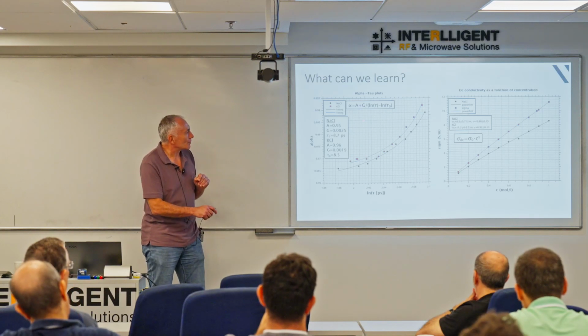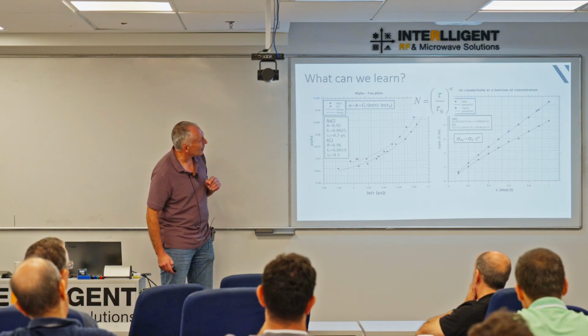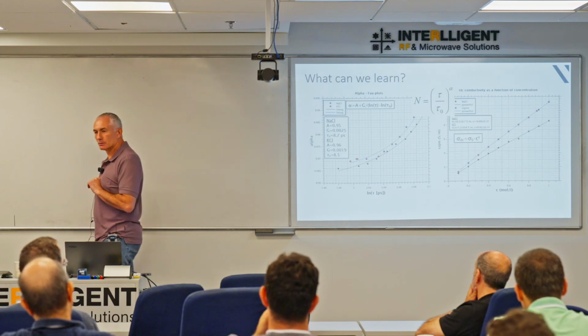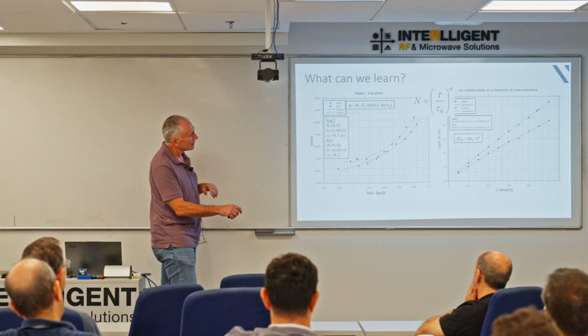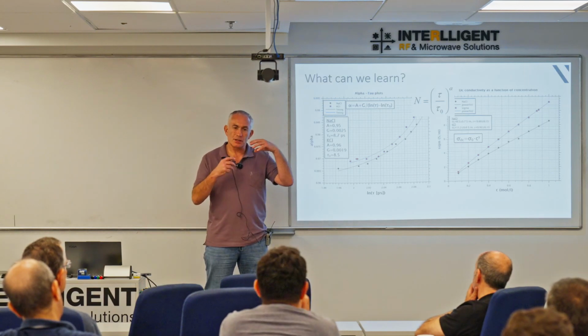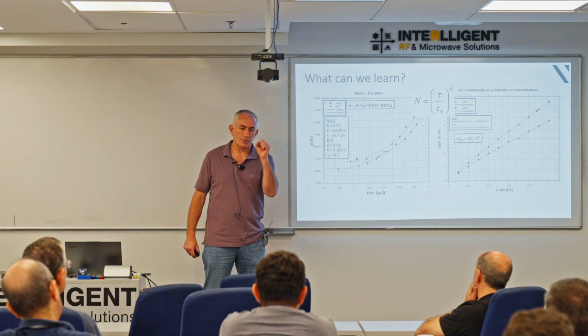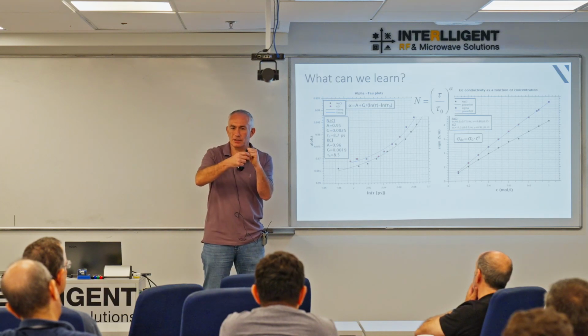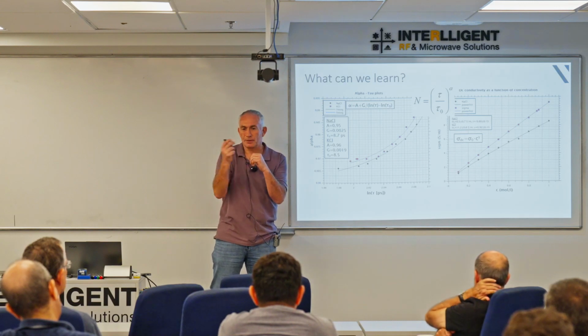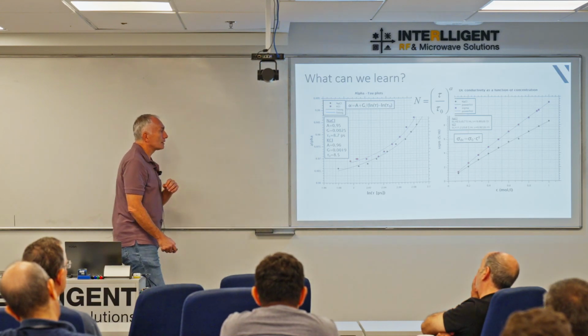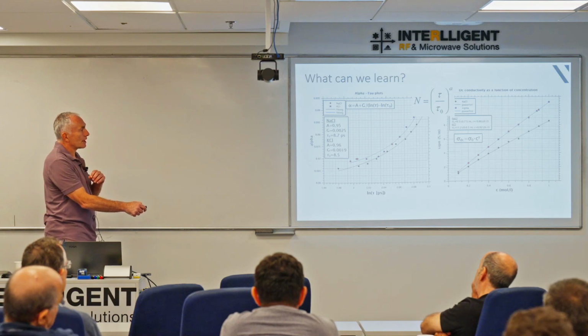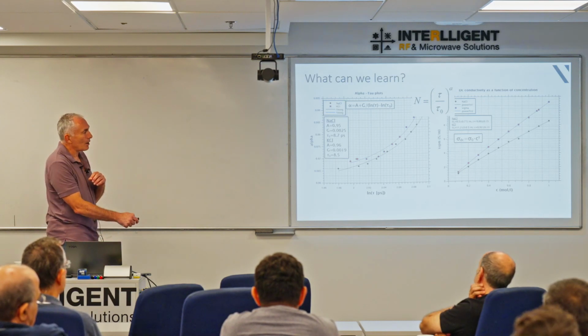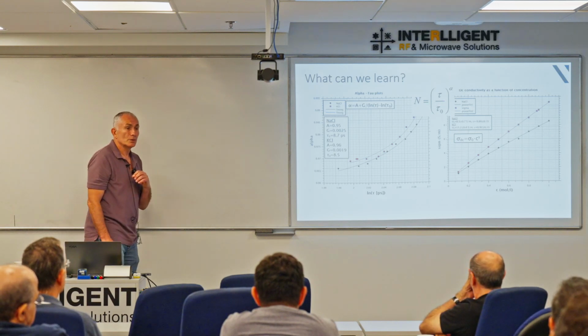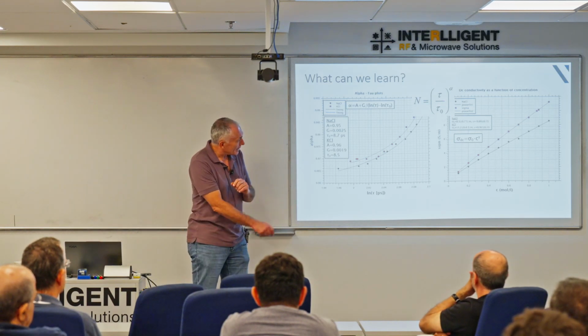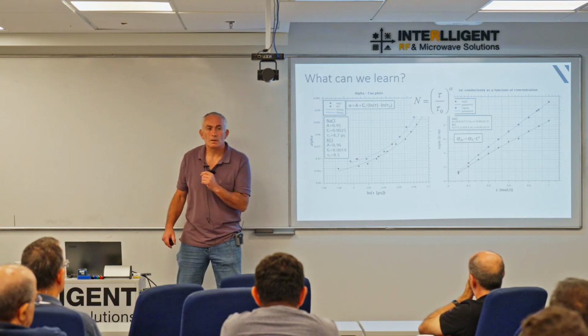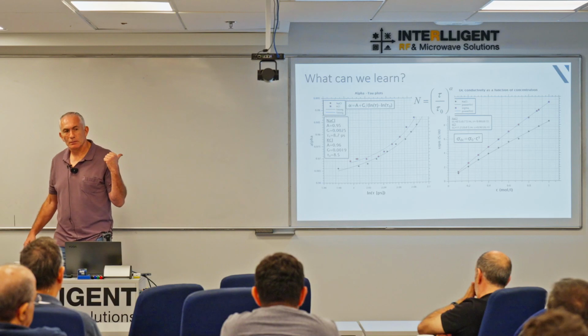So, we took that expression for alpha and tau, we changed it around. N now represents the interchange, the ability of water to move into that vicinity and to move out. How many times is it actually going to happen, if it's going to happen at all? Okay? And we now use the alpha as that scaling parameter, as that power law, relating it to that relaxation time. And it has a cutoff, a minimum, actually no, a maximum time.